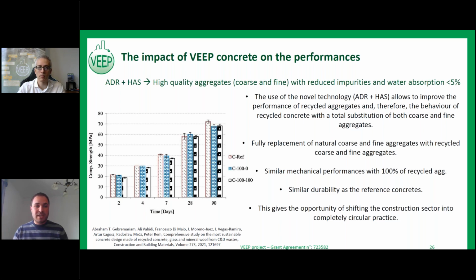So here you can see that, depending on the age of the test, more or less we are able to maintain the compressive strength, the mechanical performance, and sometimes we even increase the mechanical performance compared to the reference one. Concerning the durability, we are able to demonstrate that we have similar durability as the reference concrete. And about the workability, it's true that the workability decreased a little bit.